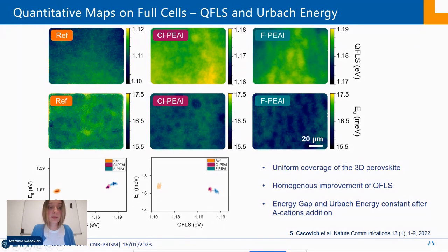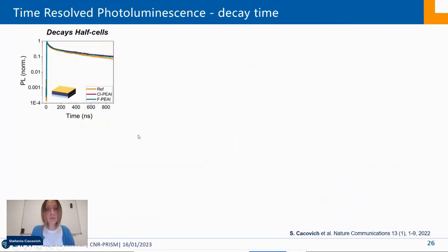We can see that the distributions are not so wide. So this means that the properties of this material are quite homogeneous. We can see there is a pretty much uniform coverage of the 3D perovskite, because here we can see that there are only small variations of these values, and that the energy gap and Urbach energy are constant after the addition of the A-cations.